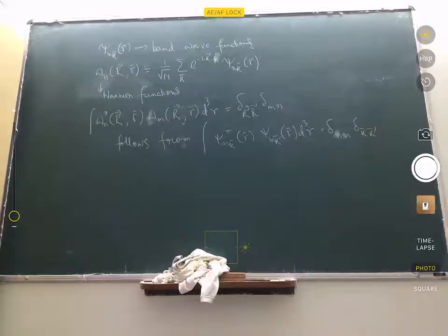So that's a very widely practiced procedure. So you do some realistic band structure calculation, maybe even including electron-electron interaction effects, get your band states, do a transform like this, get your Wannier functions which are localized, and then use those localized functions to construct your tight binding model, which will presumably be more realistic.